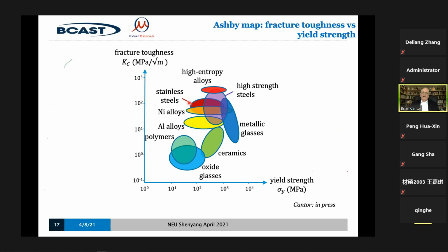Pure metals down at this end here, pure iron, pure aluminium, and they're much more resistant to fracture, but they're also not as strong as the strong ceramics. But if you then use our metallurgical development techniques, we can push their strength up like this to get high strength steels, high strength nickel alloys, and so on. But here are the high entropy alloys, including the Cantor alloys, the multi-component alloys. They've got the best combination of fracture toughness and yield strength of any materials that have yet been developed.